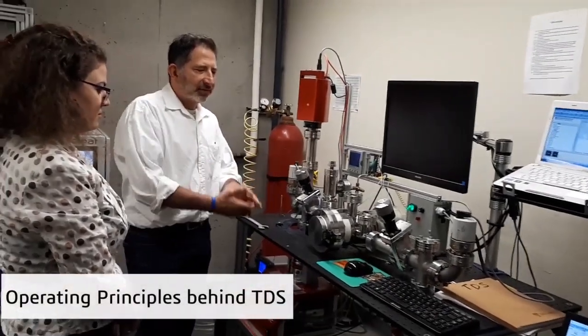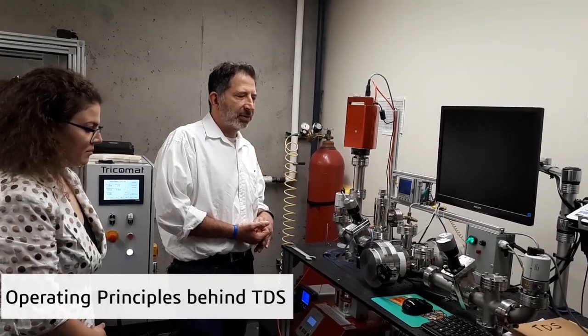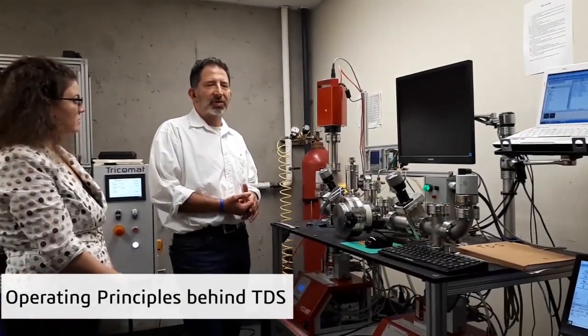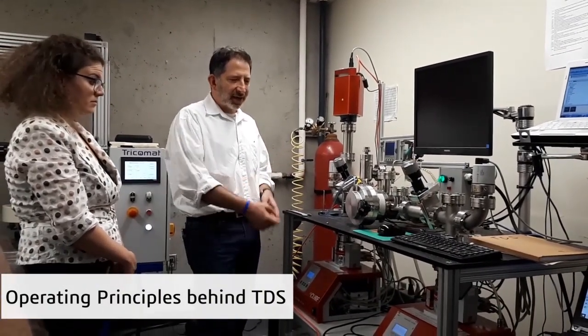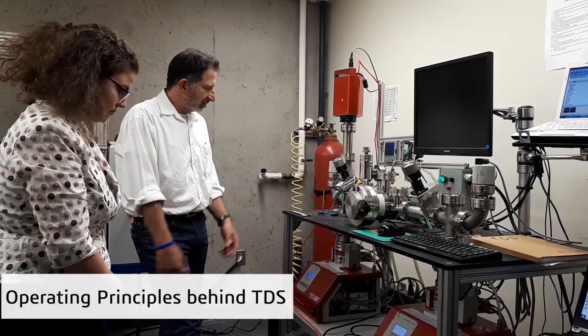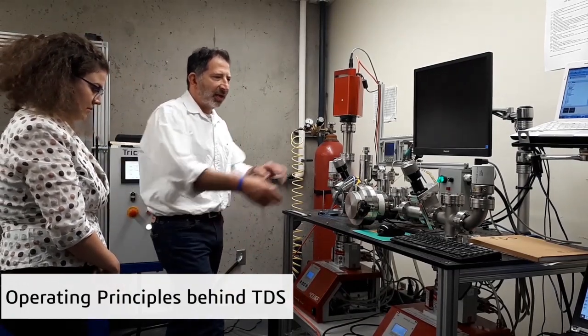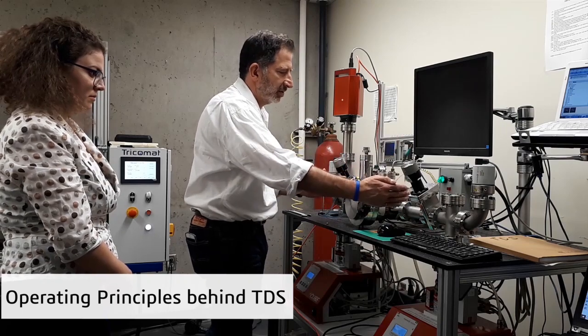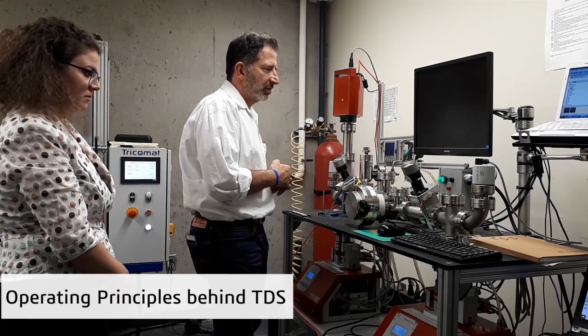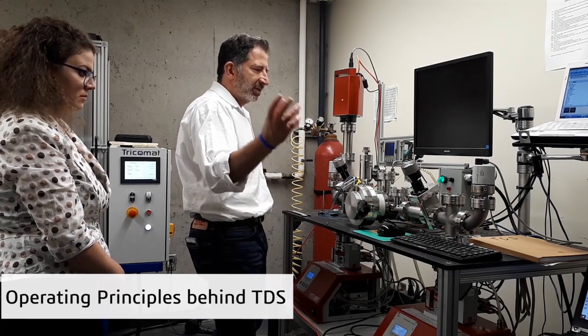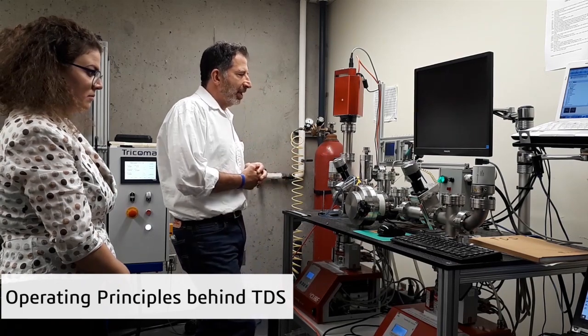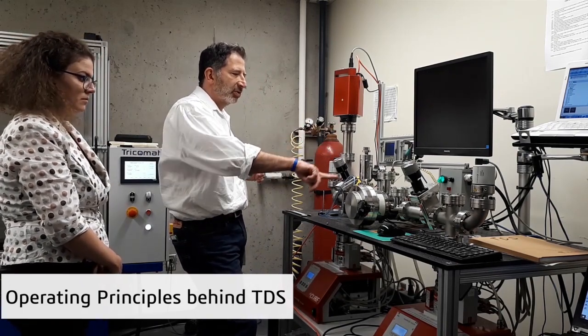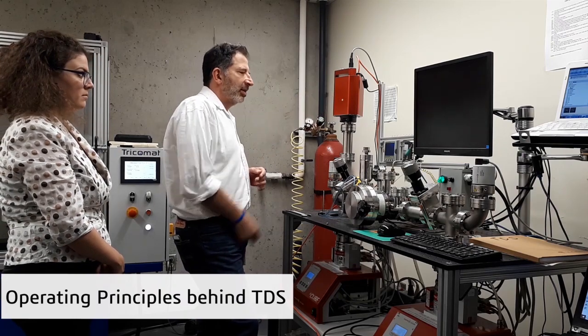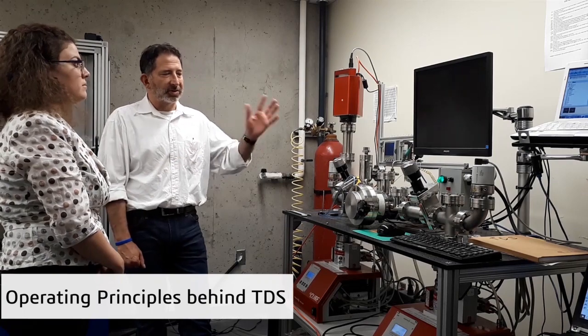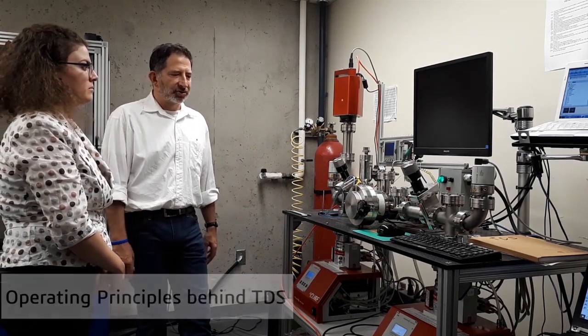The reason we have the sophisticated chamber is that in order to detect the hydrogen, we have to create a very high vacuum. We're talking about 10 to the minus 8 torr. So we have these thermal diffusion pumps and mechanical pumps designed to pump down the chamber, and valves that shut off the system or keep it open so that the stream is flowing. We pump out the system, put the sample in there, and heat it up. As we heat it, a stream flows through a mass spectrometer, which detects the elements, particularly the hydrogen, and gives us the hydrogen concentration in atoms and in molecules, and we can convolute that.